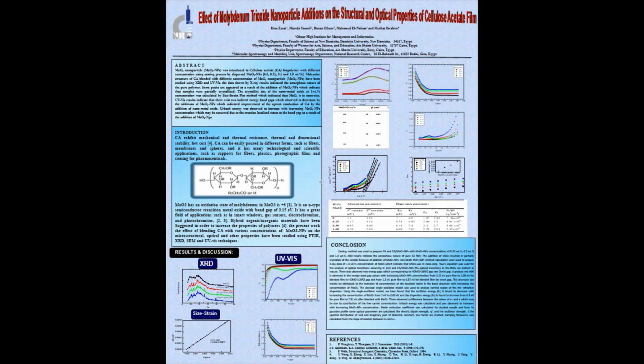The classical single oscillator model was used to analyze the normal region of the refractive dispersion. The oscillator energy and dispersion energy were calculated. It was found that the oscillator energy decreased with increasing concentration of molybdenum trioxide nanoparticles. Also, it was observed that the dispersion energy increased with increasing concentration.